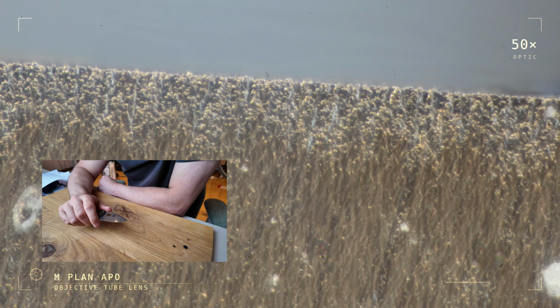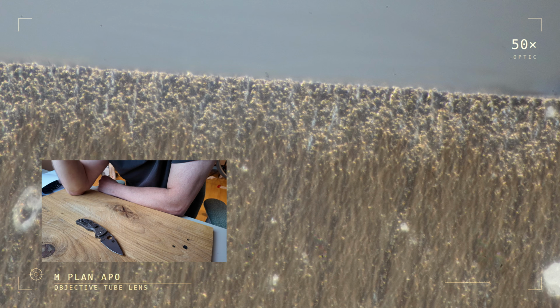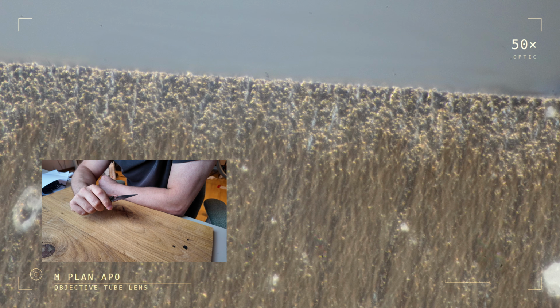Research going back more than 60 years has shown that large carbides can act as crack initiation sites. Perhaps in this one you can see the carbides even better. So if edge stability is compromised by these exposed carbides, perhaps cracks are the mechanism by which this is achieved.